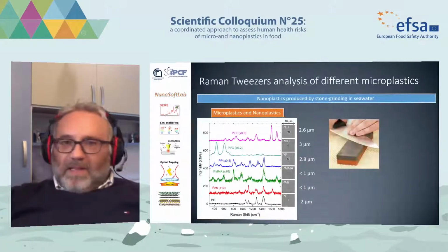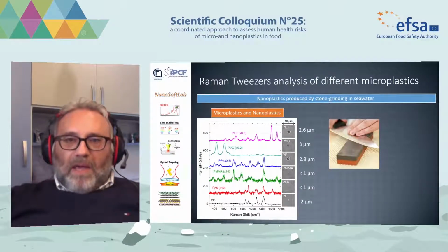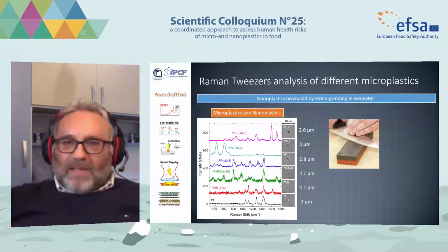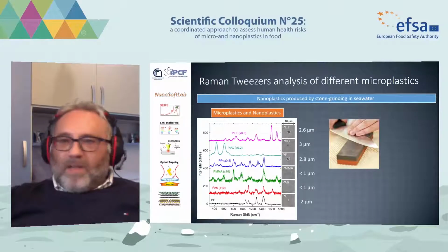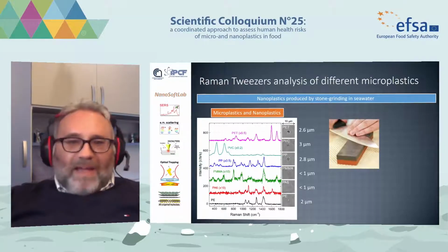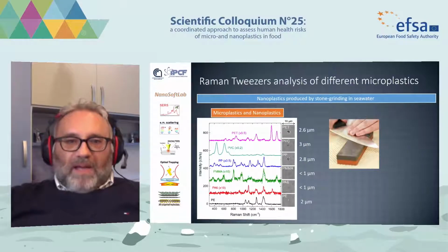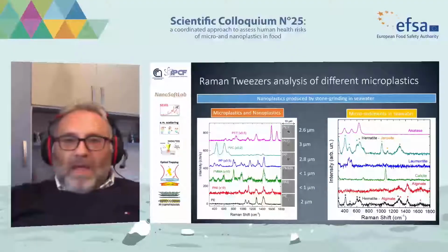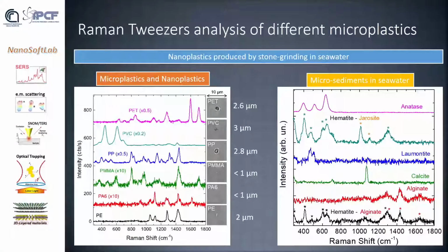Another interesting thing is that we can produce nanoplastics or microplastics by just grinding stone, then dispersing these in water, detecting them, measuring their size, and identifying their chemical species based on the Raman spectrum. For example, if we mix them into seawater, we can distinguish the fingerprints of the plastics from the fingerprints of the microsediments. So unambiguously, we can distinguish microplastics and nanoplastics from seawater microsediments.